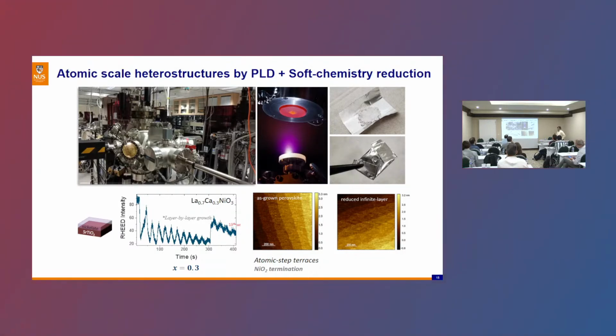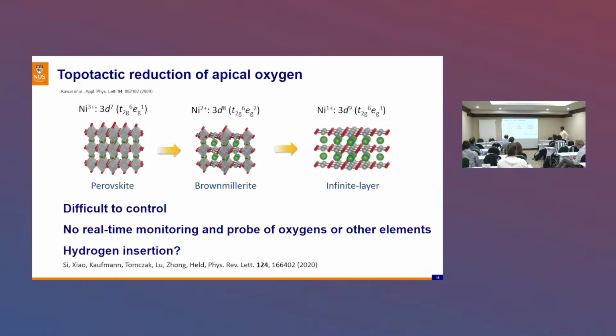So again, the problem looks like this in the soft chemistry process. Ideally, during the reduction, the oxygens will start to be removed alternatingly, right? And then as you continue this process, you will produce the infinite layer structure, all right? So this is the thing that we really have a problem with. It's difficult to control. So ideally, it would be nice if we can really look into the oxygen state, the different reduction steps, even if we can do it in real time, okay? And then Carsten has proposed the idea of hydrogen insertion in this nickelate as well during the reductions.